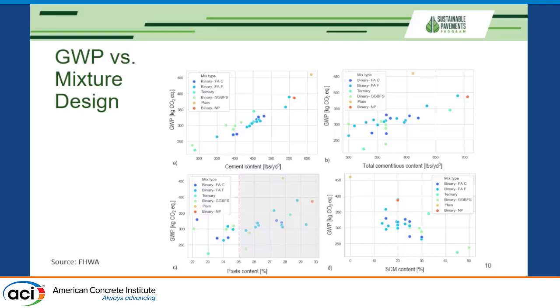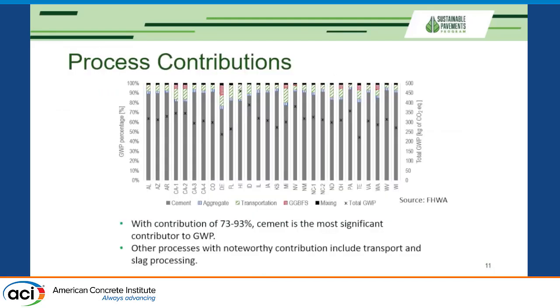So in the follow-up of this work, we have tweaked and changed mix designs, optimized these 17 mixes, and we also analyzed how much carbon we can save just by doing that. We are optimizing these mix designs by providing different aggregate gradations that allow for better aggregate packing and achieve the same results with lower amount of paste. Final graph here is the correlation between supplementary cementitious materials content and global warming potential. You can see negative correlation here, so higher SCM content also means lower global warming potential, and the exact trend depends on the mix design and SCM replacement percentage.